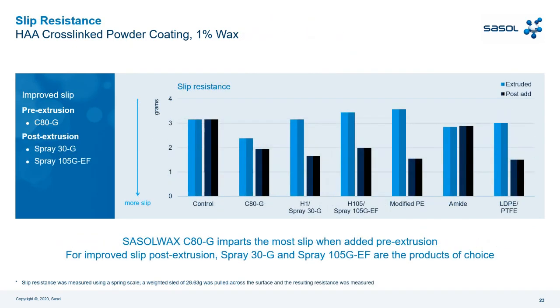Then we come to the slip resistance in HAA cross-linked powder coating. So slip performance you can have in pre-extrusion or in post-extrusion, it depends on you, it is up to you. So Sasol wax C80G imparts the most slip when added in pre-extrusion. You can see here that the control has a very high value. You need to check the lowest. Then in post-extrusion, we have two options, Sasol wax spray 30G that has the best value, similar to the HDPE, or Sasol wax spray 105GEF that follows for Sasol. For Sasol wax spray 30G, we have a similar result respect HDPE and LDPE and PTFE for slip resistance.